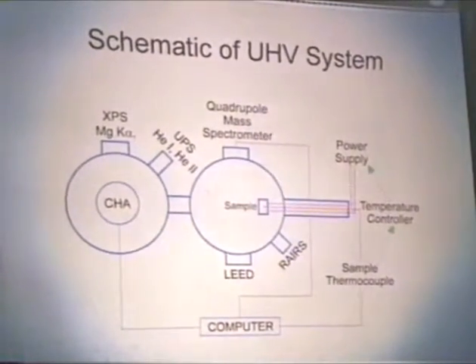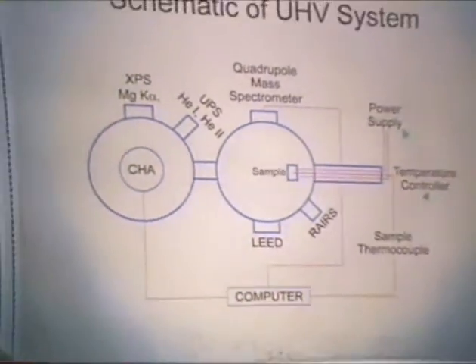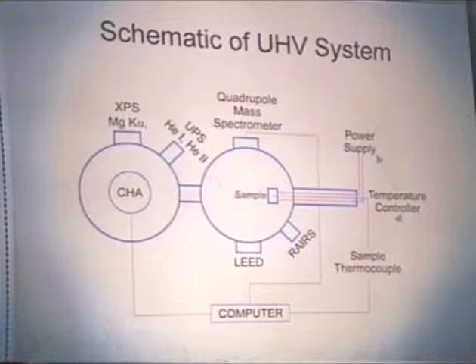A simple schematic of the ultra-high vacuum system that I use. It consists of two interconnected stainless steel ultra-high vacuum chambers. Both are equipped with turbomolecular pumps as well as titanium sublimation pumps and can be cooled cryogenically to remove condensable gases from the background. The chamber on the left we refer to as the analysis chamber, and it contains a concentric hemispherical analyzer for analyzing the energy of electrons, as well as an X-ray and ultraviolet photon source for XPS and UPS, respectively. The chamber on the right is the preparation chamber, and it is equipped with a quadrupole mass spectrometer, LEED reverse view optics, and IR transparent windows for reflection absorption infrared spectroscopy.